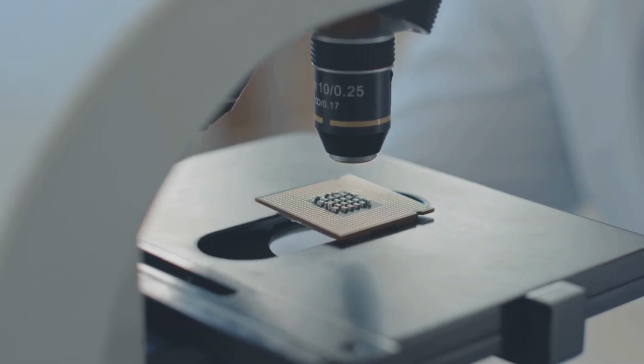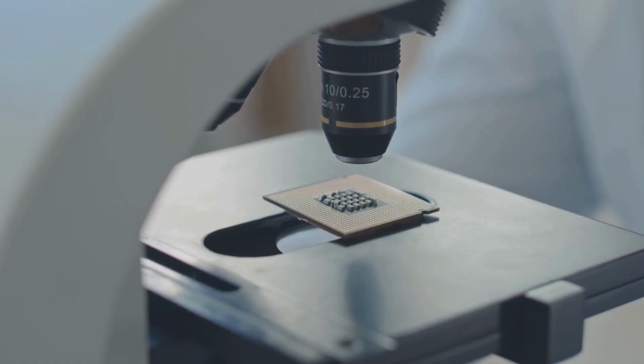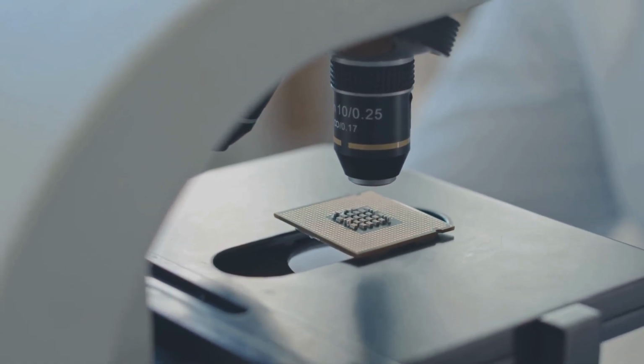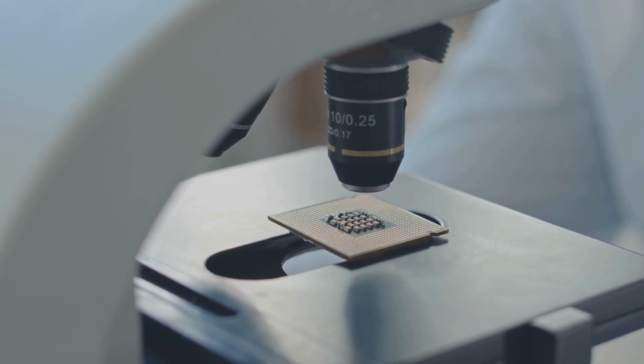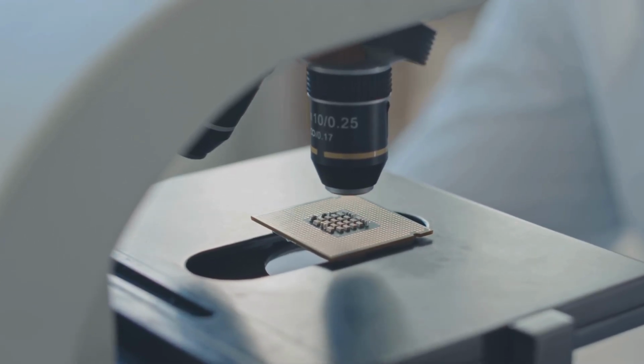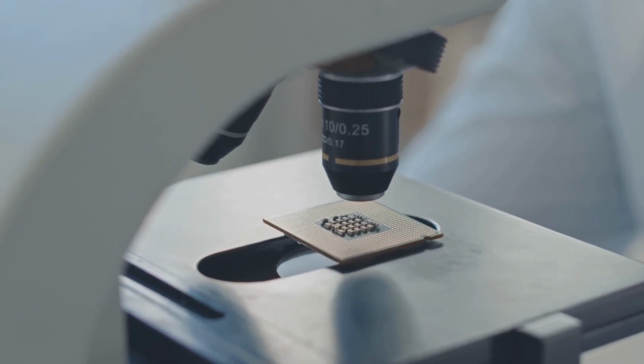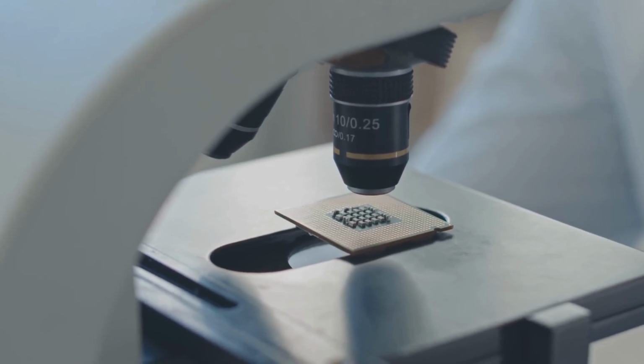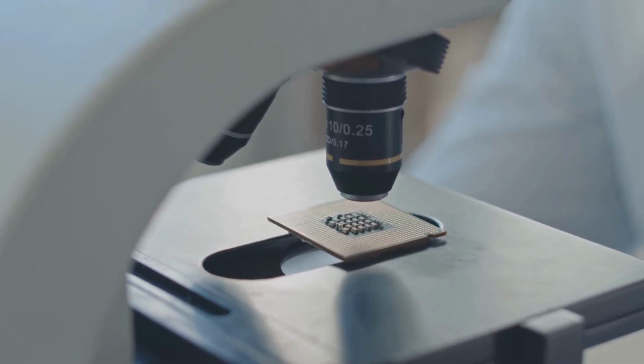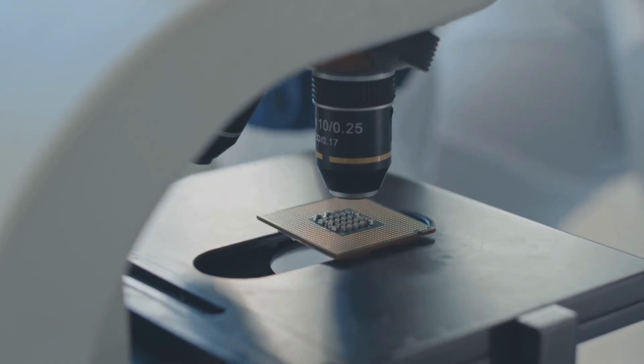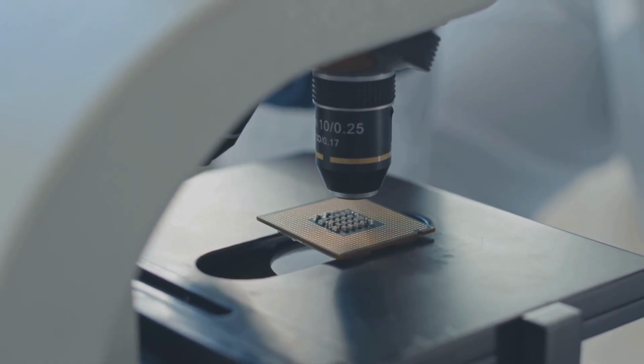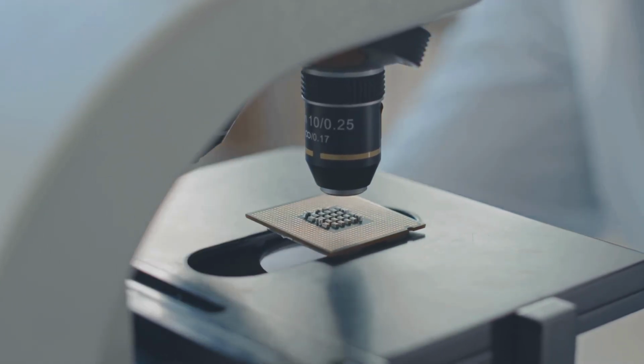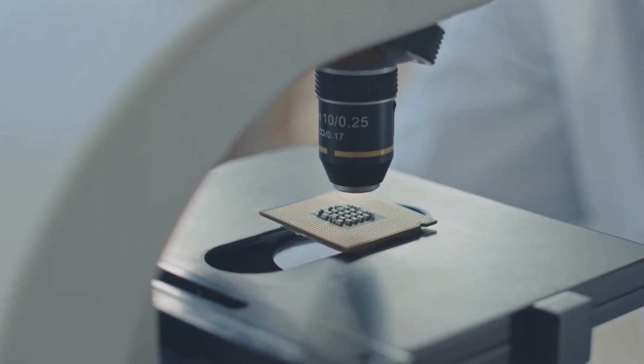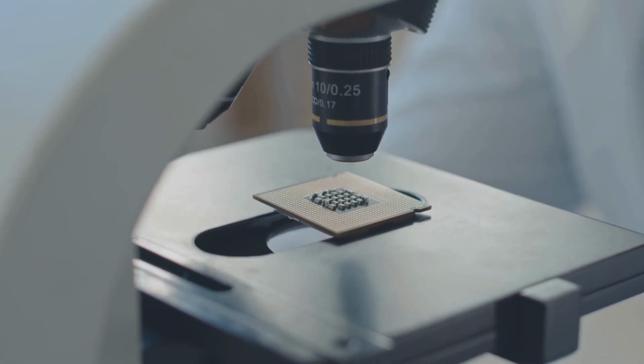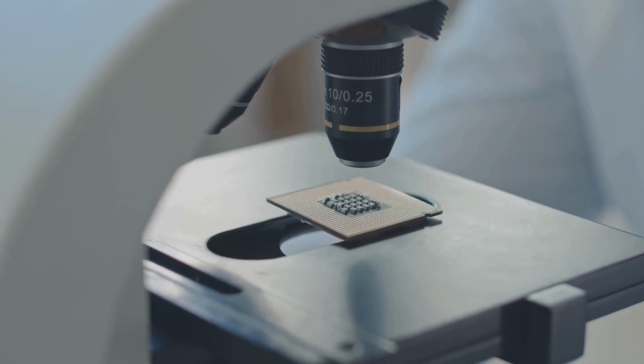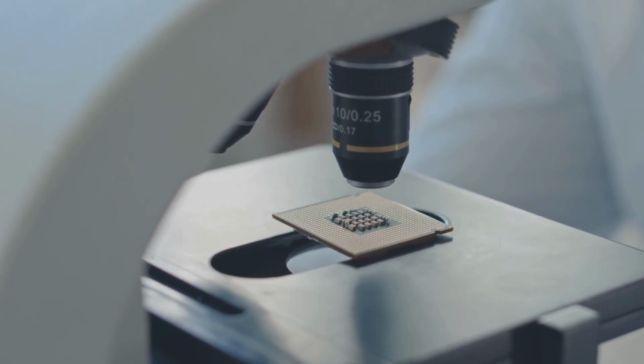The legacy thermal architecture bonded the cell to copper. Copper expands at 17 parts per million per degree Celsius. The gallium arsenide cell expands at roughly 6. That is a mismatch of 11 parts per million. When the assembly cools, the copper contracts more than the semiconductor, pulling the cell into tension. Gallium arsenide is brittle in tension. The tensile stress caused gridline microcracking and, in severe cases, instantaneous fracture of the cell edges. This was a documented failure mode of legacy CPV receivers.